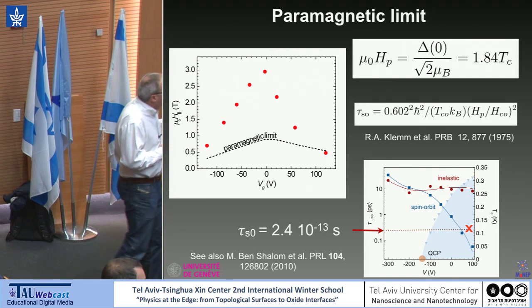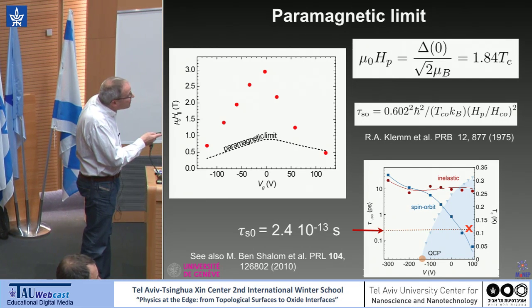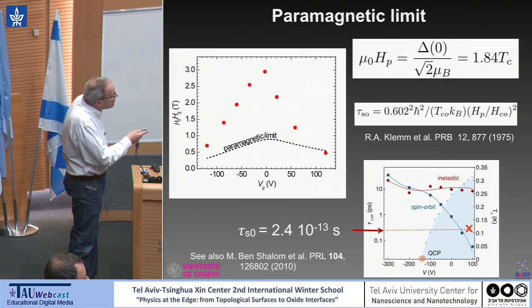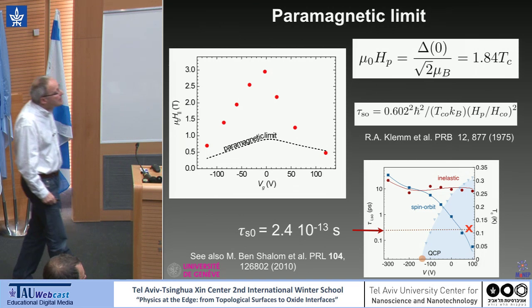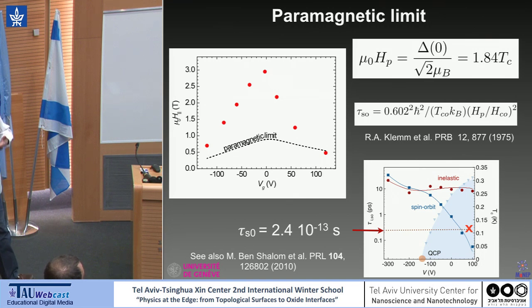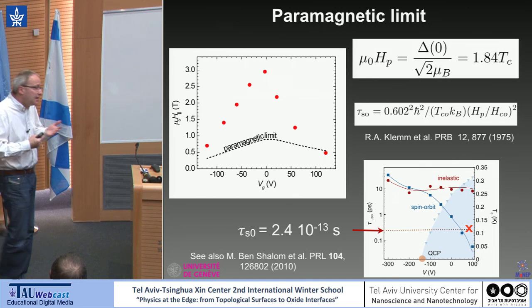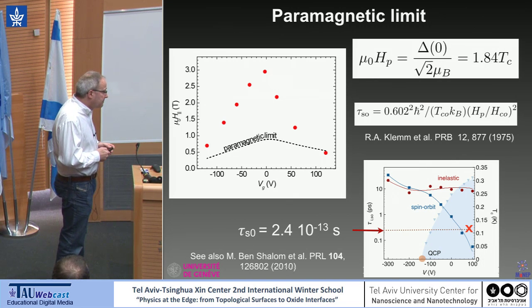And if you do this analysis, and we did it here, you find, okay, and I didn't show this graph, but this is the spin orbit scattering time versus gate voltage. This is what we get from transport, and this is what you would get from this analysis. So it could be that this enhanced parallel critical field is indeed linked to spin orbit.